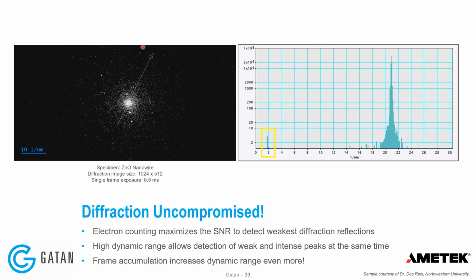On the left-hand side, you're looking at a single diffraction image with 0.5 millisecond exposure time. And what I've done is I have drawn a profile line along my direct beam, the high intensity beam here, and this reflection, the high resolution reflection, all the way on the top here. You see that profile line in logarithmic scale on the right hand side. The yellow box here is showing the intensity from this reflection. You can see it's like 4 or 5 counts, as opposed to several orders of magnitude more counts here for the intensity at the direct beam. So this is directly showing you the dynamic range of the camera.